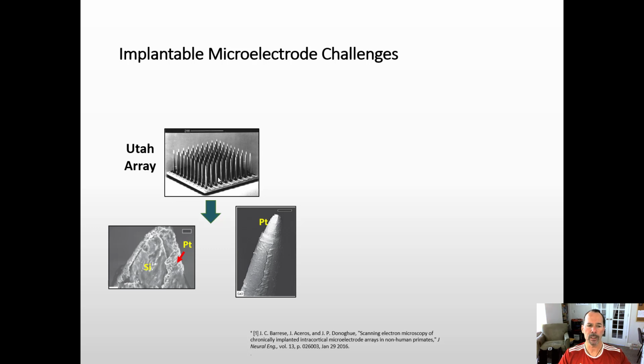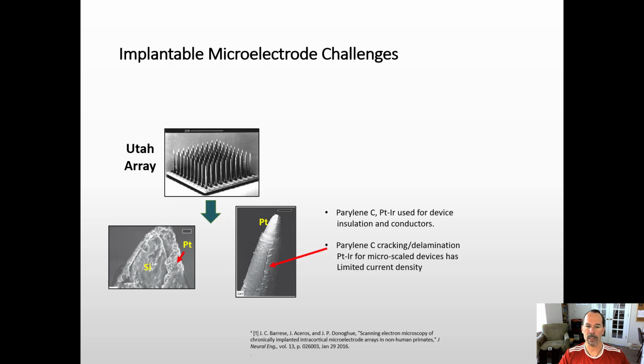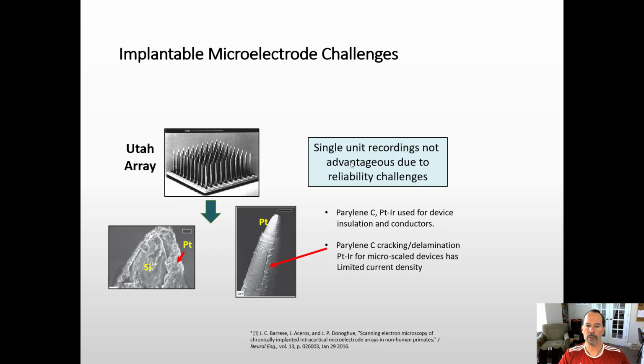So basically, if we had used silicon carbide, cubic silicon carbide as the support, these types of reliability failures wouldn't really cause us catastrophic failure, and we believe that's why this solution we're proposing makes sense. So again, this cracking and delamination is a challenge. Single unit recordings were not possible with these devices due to reliability challenges. So if we want to have highly accurate neural connection to a device, we need to be able to do single unit recordings, and it's currently not possible with this technology.